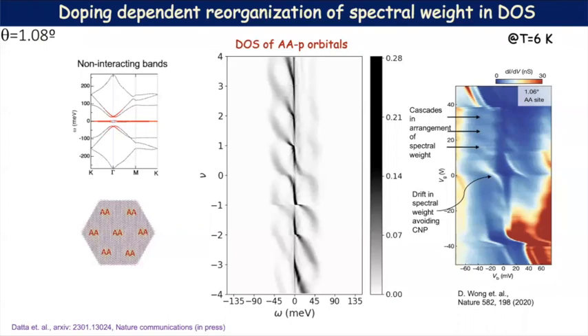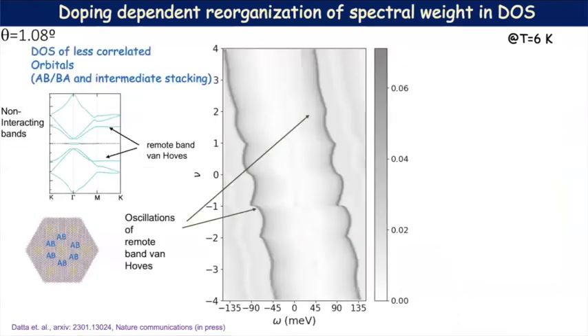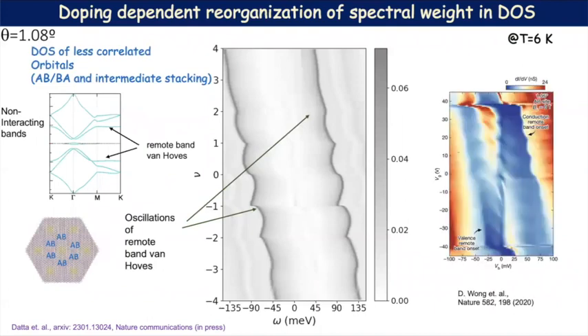And then the other part of the picture comes from the less correlated orbitals, which are in the AB/BA or the intermediate stacking region, which has these oscillations at higher energy. These oscillations are actually coming from the Van Hove peaks, which are in this remote band in the M-K direction. Now if you look at the corresponding experimental figure, which is the dI/dV map on the AB site, you can see that there is a beautiful match between the two.